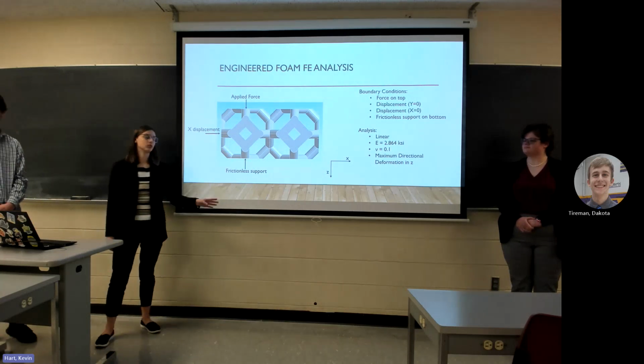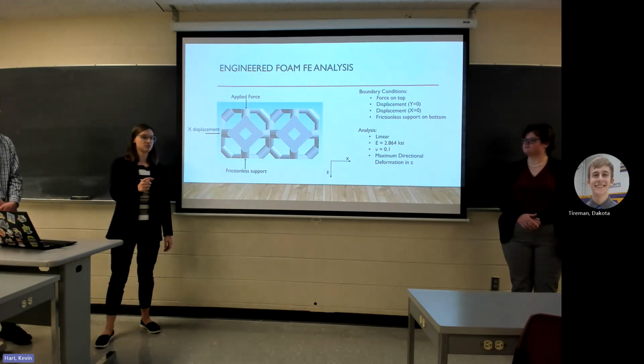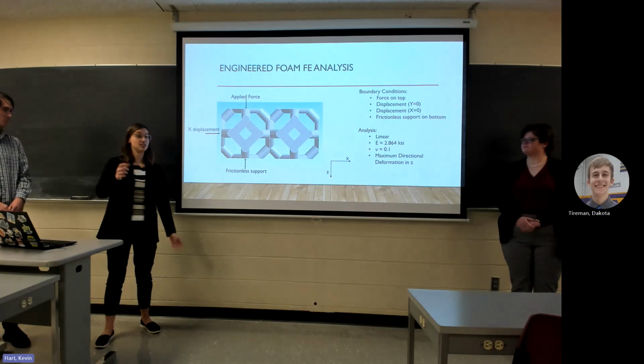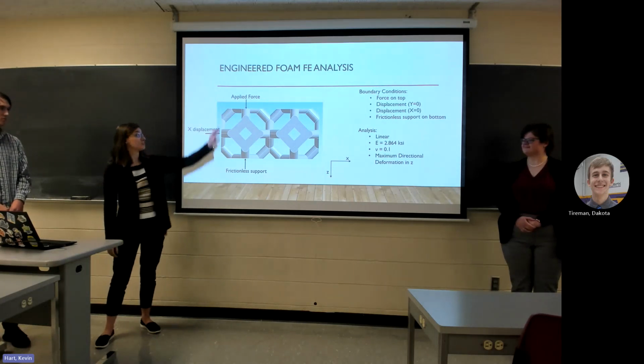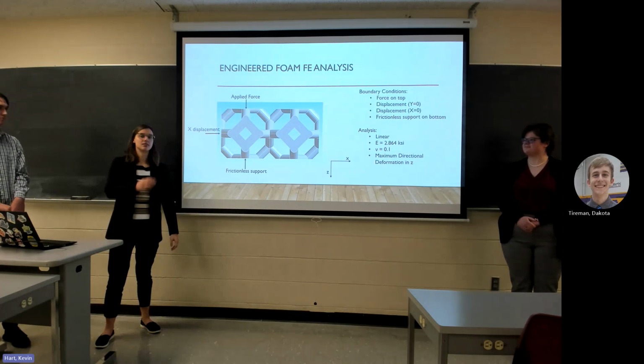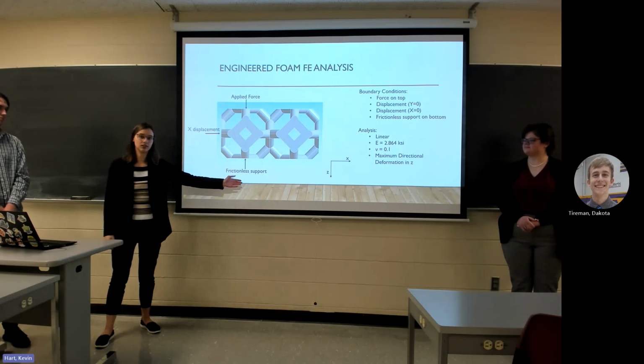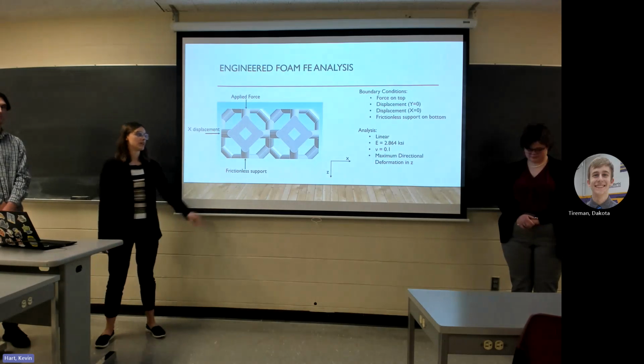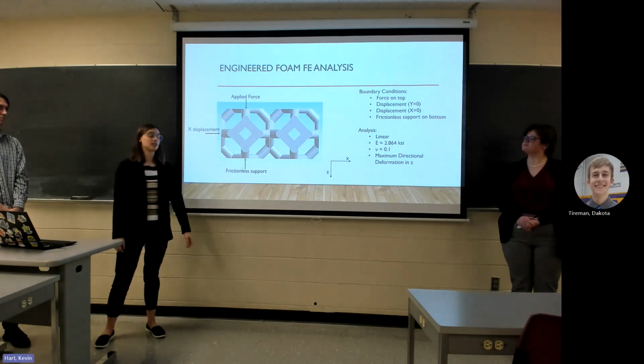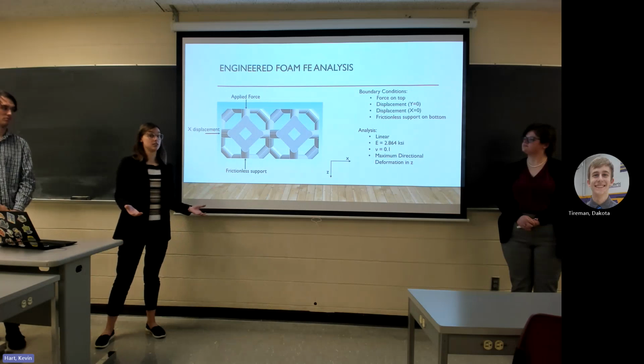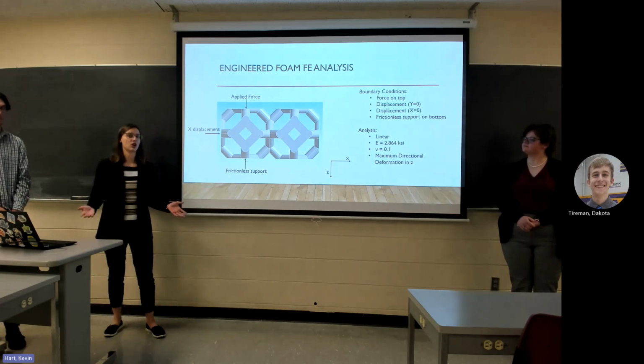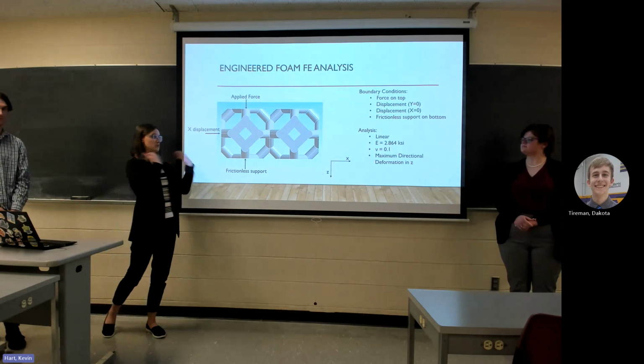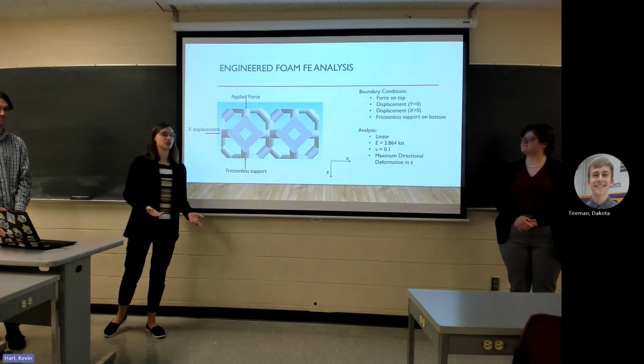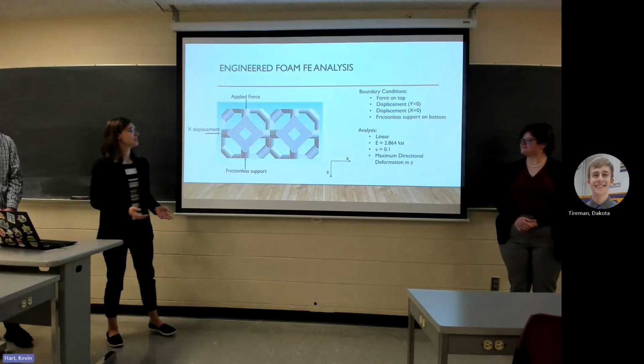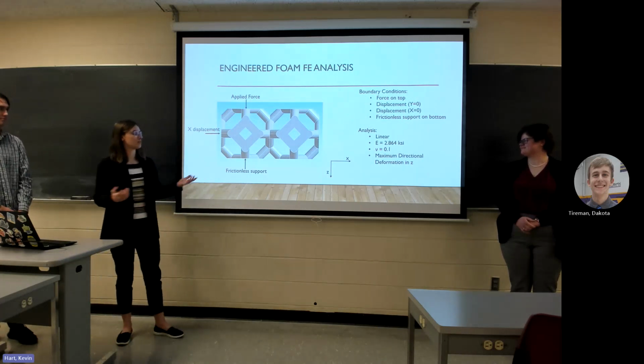When we switched to the linear approach, we noticed that the deformation from the nonlinear to the linear didn't change at all. So if I had 20 newtons applied on top and the deformation in nonlinear was 0.002, the same thing happened in the linear when I did it. So that helped us kind of validate that we don't have to do this in nonlinear, and it'll be easier on the software and for us to be able to model more, because nonlinear took hours to run sometimes, and it didn't help us get anywhere too fast.